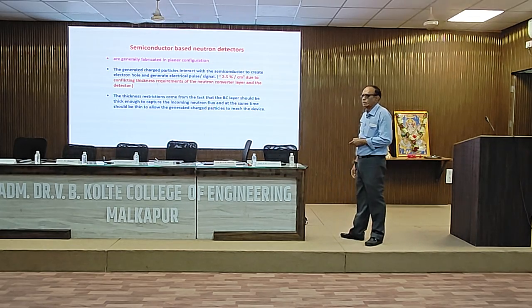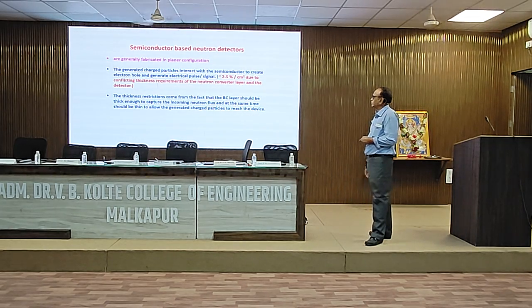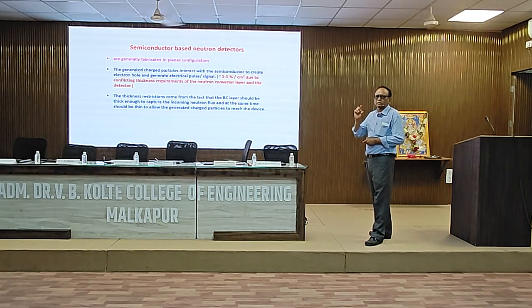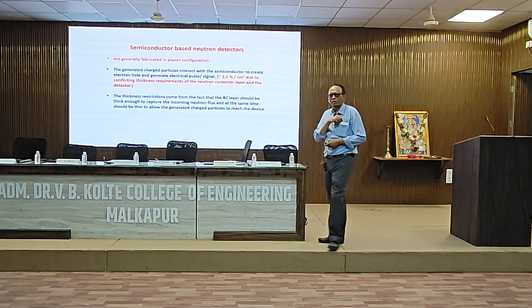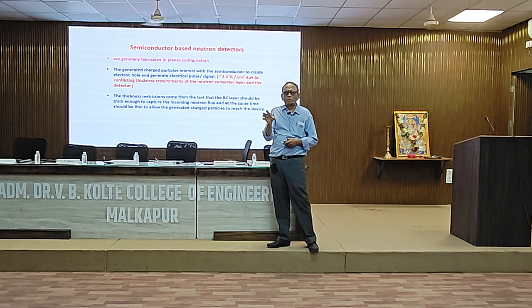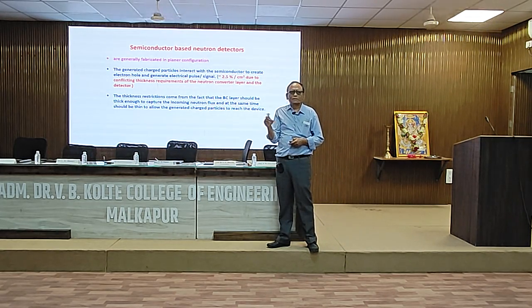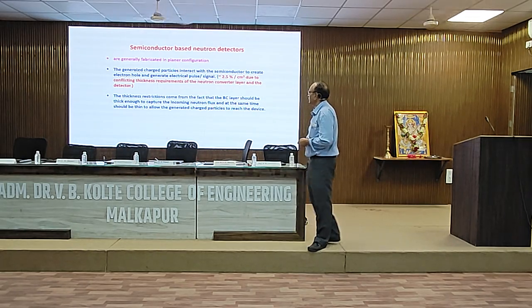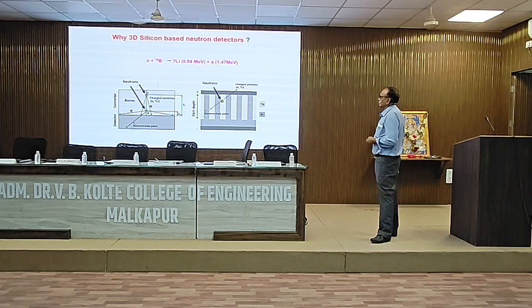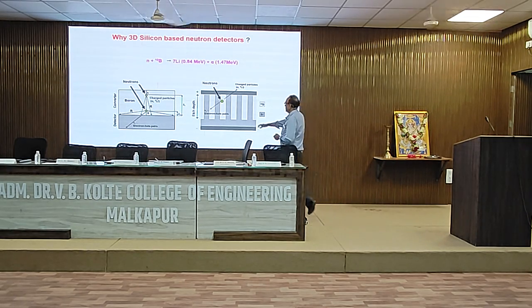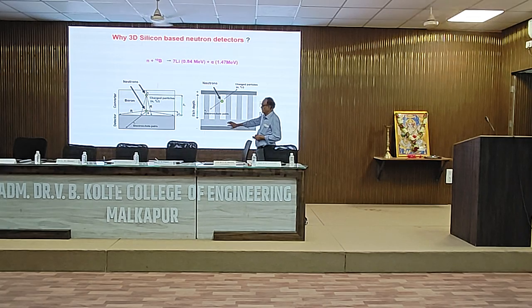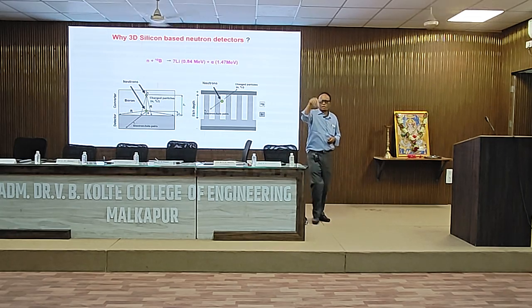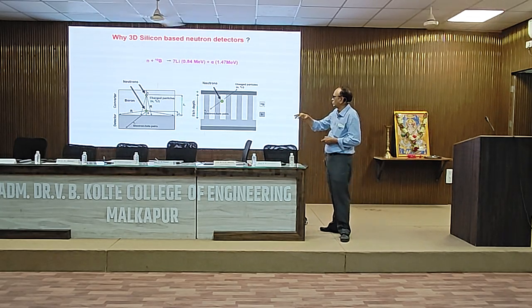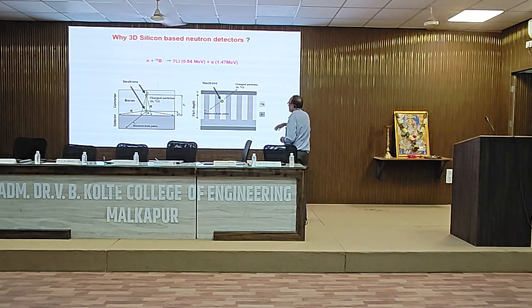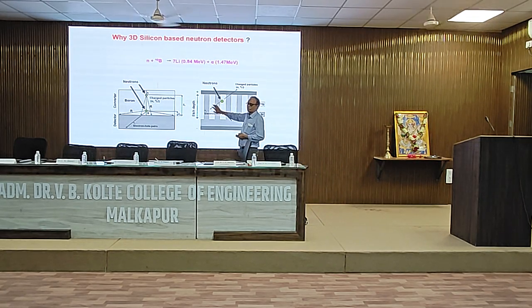So we are developing something on this semiconductor-based neutron detector, so that the neutron detector can be of the size of a cell phone, and with the security people, both in the atomic energy establishment as well as in airports, etc., these devices can be used. So basically, here you have the semiconductor PIN diode, in which there are trenches. This typical trench size is 4 micron by 4 micron and depth of 25 micron. That is the one on which we are working. Then in these trenches, you fill boron carbide.